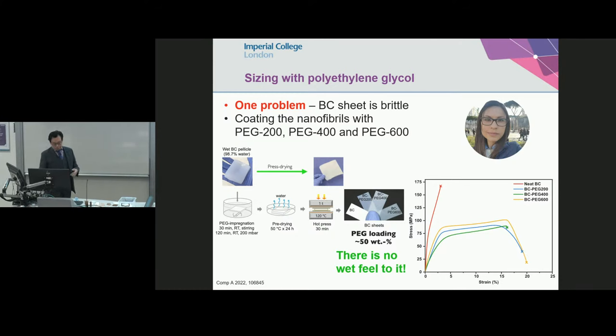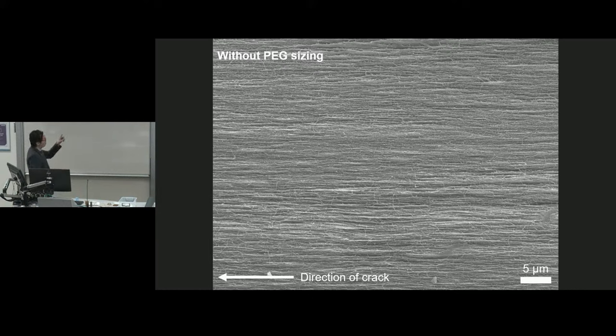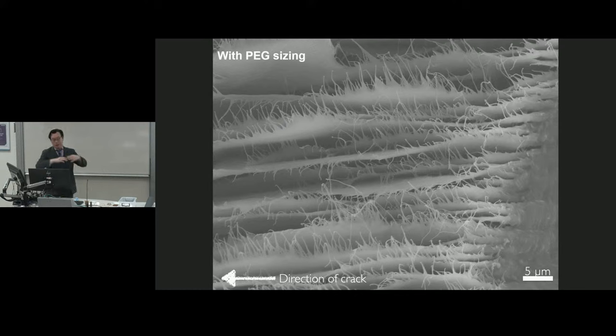The reason why it works is because without that coating, this is one of the fracture surfaces. So you pull it apart, it fractures. You take a look at it, what happens during fracture. You can't see much. All you see is clean fracture. With that polyethylene glycol, you start to see the fibers. We get sort of a fibrillation process where you actually start to see the fibers coming up. And the reason is because with that polyethylene glycol coating, now upon pulling, upon deformation, you are able to rotate the fibers. So that gives that plasticity until it sort of slides and slips out from each other, giving rise to that ductile behavior that you see earlier.